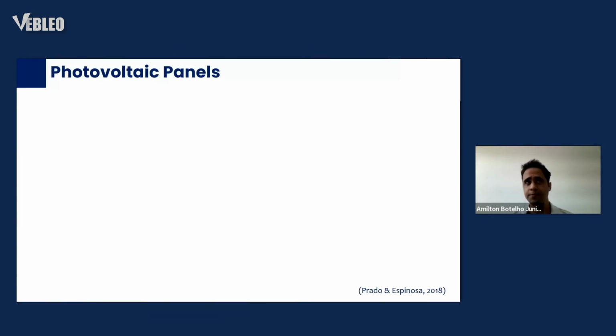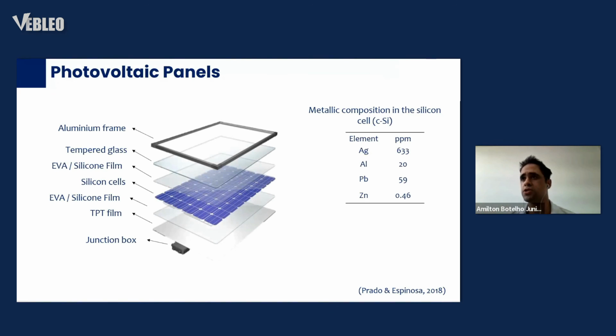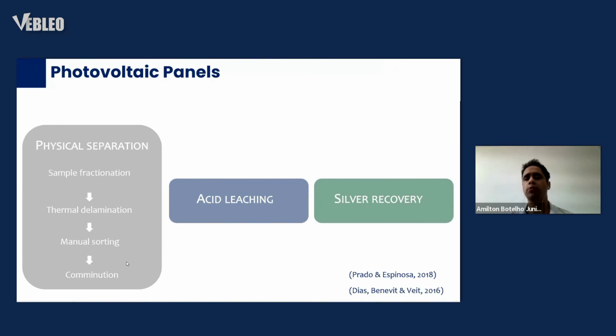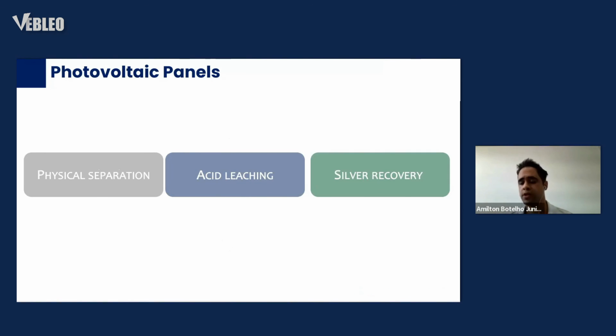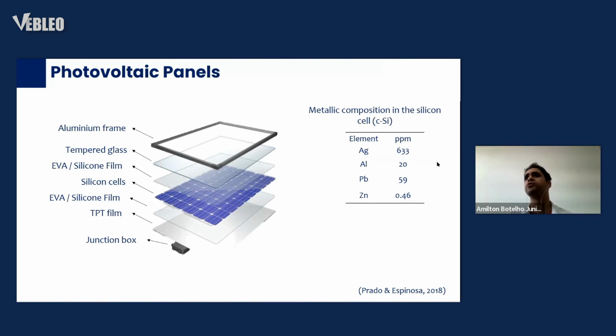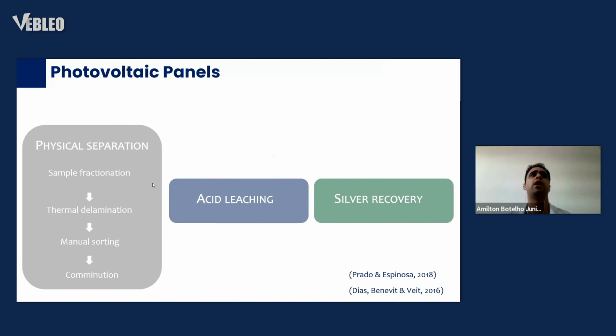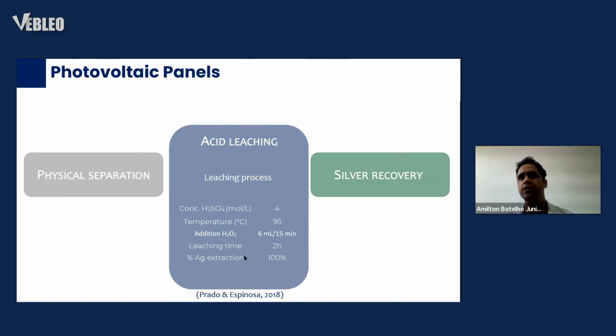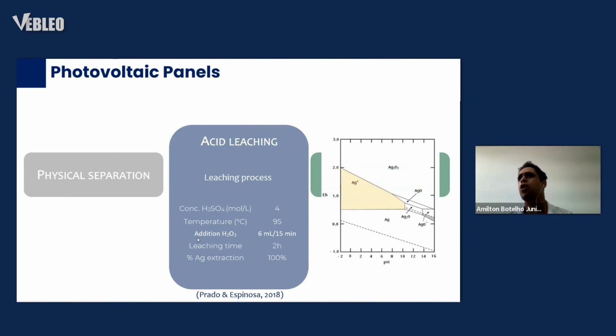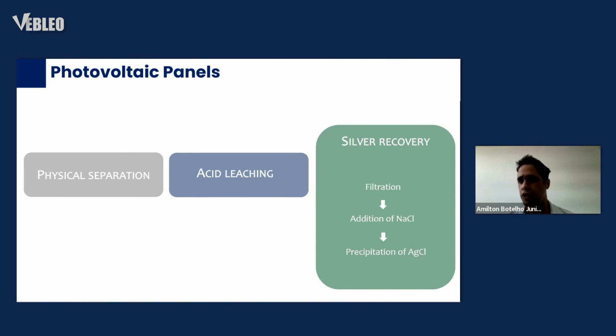Finally, the photovoltaic panels. It's important because of the increased demand and the change of behavior to improve energy metrics in the world. So the consumption of photovoltaic panels has increased. First, physical separation to concentrate the fraction with silver. The most valuable element in the photovoltaic panels is silver. So the physical separation is important to concentrate silver, and then leach also using sulfuric acid and hydrogen peroxide, and finally obtain silver as silver chloride.